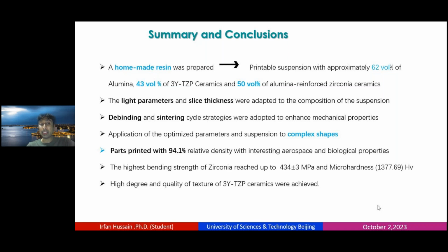Then the light parameters and slice thickness were adapted to the composition of the suspension, and the debinding and sintering cycle strategy was adopted to enhance the mechanical properties. With application of the optimized parameters, complex shape parts were printed with a maximum of 94% relative density, interesting for biological application, and the highest bending strength was achieved with zirconia.